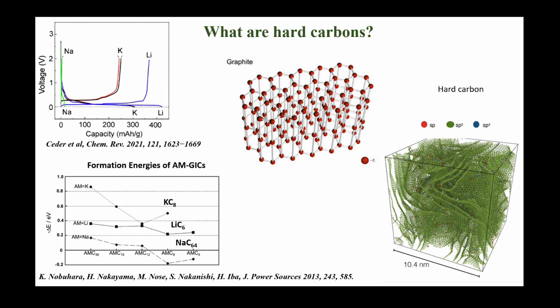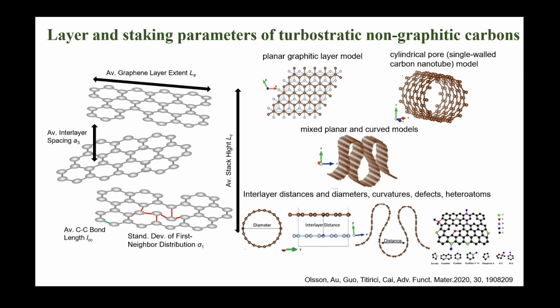So if lithium and potassium go into graphite, sodium cannot, but very happily goes into a hard carbon, which has this type of disordered structure. And hard carbons are complicated. And in order to really understand the best hard carbon for sodium storage, you really need to understand it atom by atom and how sodium stores into this carbon. So that's what we've been doing for a very long time.